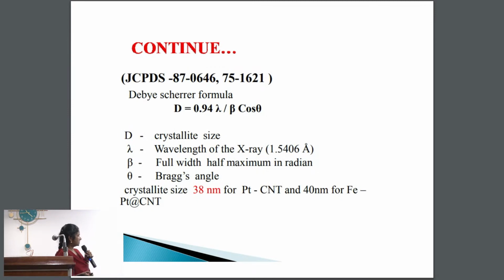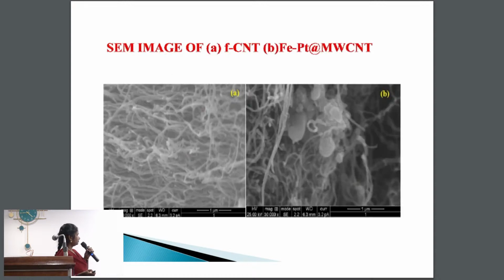Then the crystal structure was analyzed using the Debye-Scherrer formula, D equals 0.94 lambda divided by beta cos theta. The estimated average crystallite size is 38 nanometers.